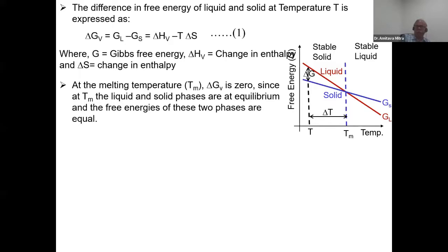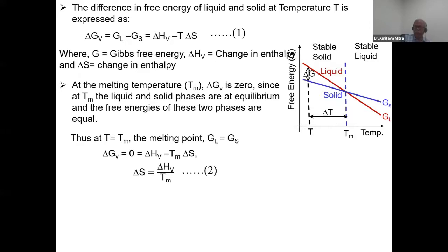At the melting temperature, delta GV is 0. Since liquid and solid are at equilibrium at T equal to Tm, GL is equal to GS, and from there we can get the equation: delta S, the change of entropy, is equal to delta Hv divided by Tm, the melting temperature.